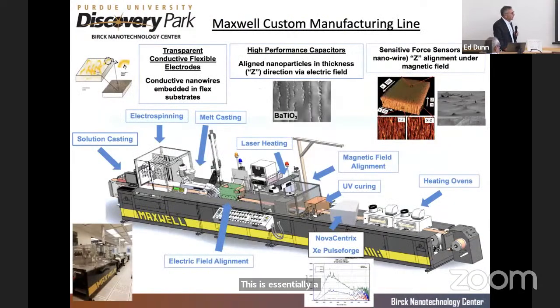This Maxwell that we've designed in my group has multiple functions. You can deliver any type of material, solution, monomer, or a melt, onto a substrate. You can functionalize it by, for example, electrospraying or electrospinning nanofibers. This happens to be a transparent conductive film that we developed that has conductive nanofibers embedded in it, so that the delamination issues are eliminated for flexible transparent electrodes. And melt casting is also possible to exclude the solvent from the process.